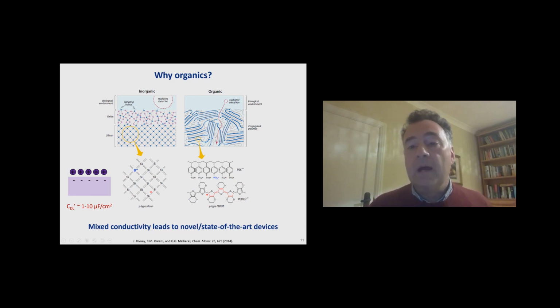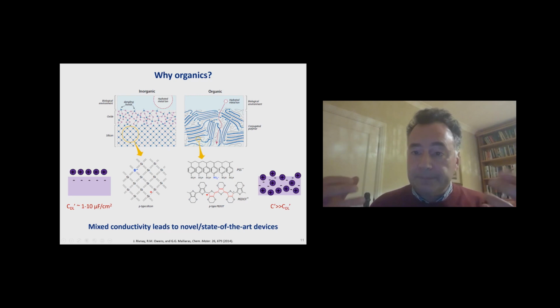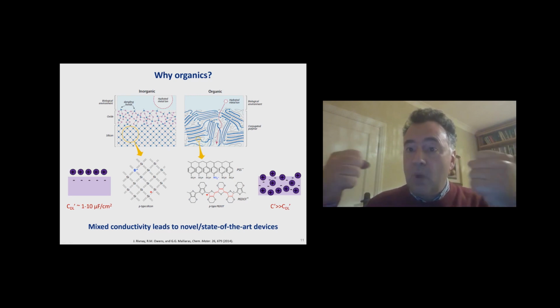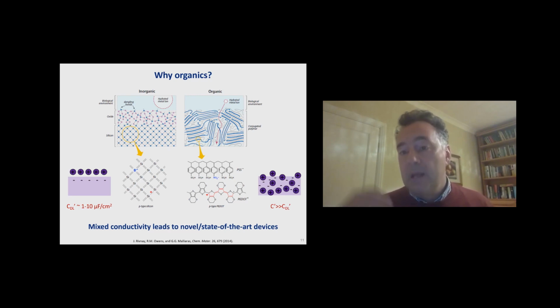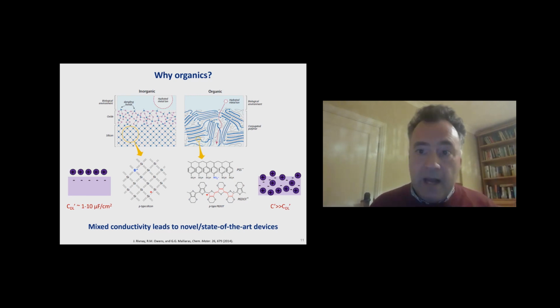On the other hand, if you use a material in which ions can penetrate into its volume, and this would be a so-called conducting polymer. We're going to overlook chemical details here. Just consider this as a spongy-like material in which ions can penetrate. Then you would have coupling in the whole volume of the material. So ions and electronic charge will couple much more strongly. So you increase, in a sense, the communication strength between brain and electronics.